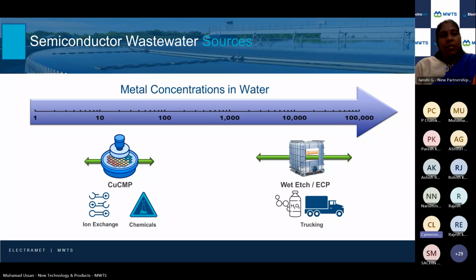And this is because there are a variety of different types of wastewater in the semicon site that are very, very different. And the incumbent solutions are designed to treat one but not the other. And so the net result is an inefficient process that is really unsustainable. And the two main sources are shown here. The copper CMP is the chemical mechanical planarization process. This is where they polish down the wafer to make it nice and smooth for the chip manufacturing. This is typically processed in-house for wastewater, and it uses probably 30 to 40% of the total water in a fab facility. And then on the extreme side, you have these wet etches.